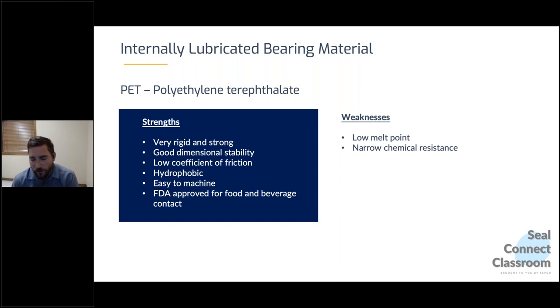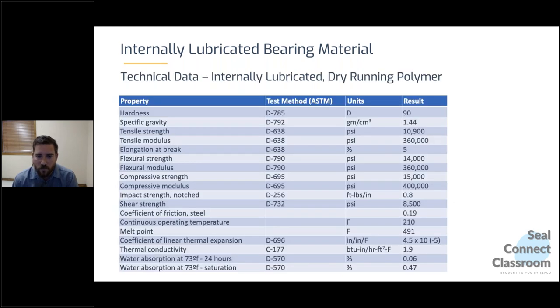So these would not be suitable for any type of harsh chemical service or any type of service where temperature is above, say, 200 to 210 degrees. But anything below that and anything that is wastewater or it's just low to no chemical service, these materials are great. Very strong, very rigid, great dimensional stability, very low coefficient of friction. They're hydrophobic, meaning they're not going to absorb water over time, so they're good for underwater applications. Very easy to machine. They're FDA approved, so these are the workhorse of that kind of non-chemical, lower temperature applications. Here you see just some technical data on this material in particular, which is an internally lubricated dry running material.